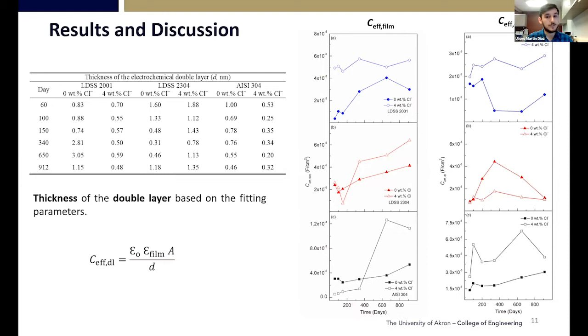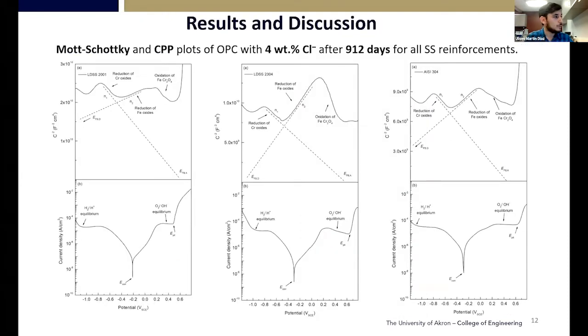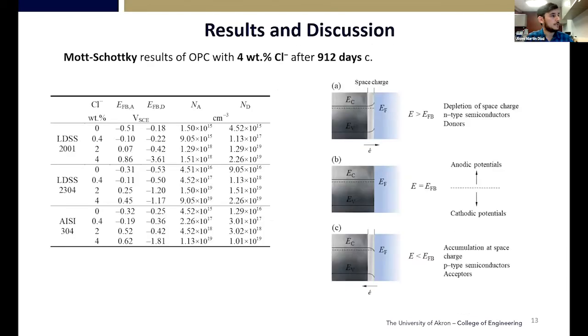Following with the semiconductor properties, we saw that all 3 stainless steels show the 3 typical peaks that we previously presented: the reduction of chromium oxide, the iron oxide, and then the oxidation of the spinel and chromium. A more in-depth analysis of this Mott-Schottky plot was seen by the flat band of the acceptor and the donors, as well as the carrier density of the same.